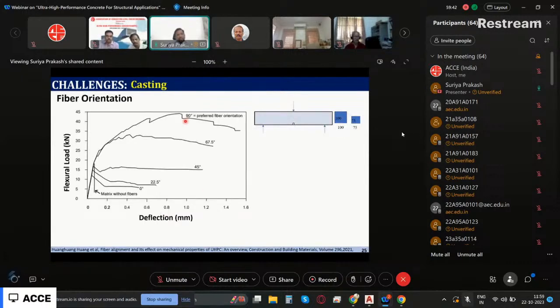Then again, fibers. When you do a regular casting at a big level, you cannot really guarantee what will be the orientation of the fiber. Let's say this is a beam that we are testing and you put a notch. If fibers are perpendicular to this notch, then it will arrest the crack better. So that's why you see the flexural performance is much better for a 90-degree orientation. If your fiber is parallel to the crack, then it will not do anything.